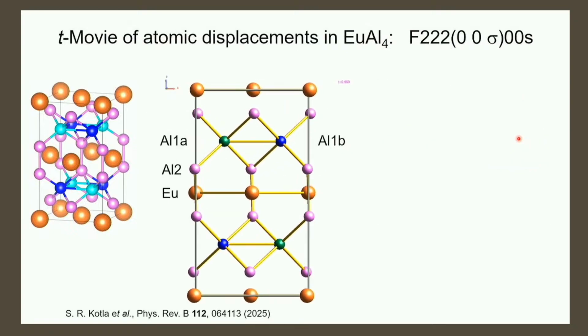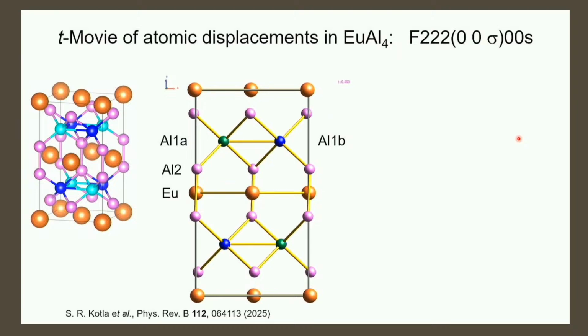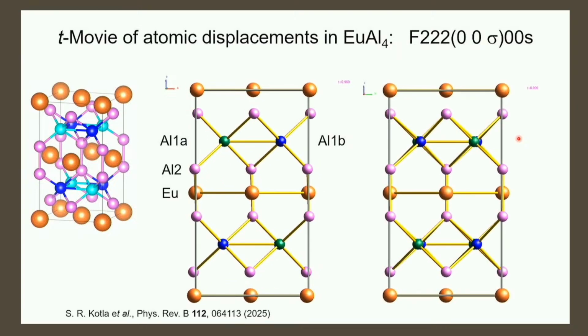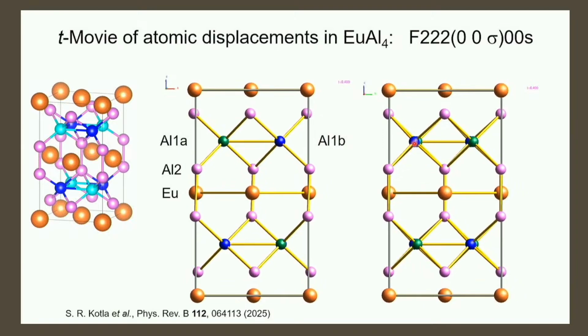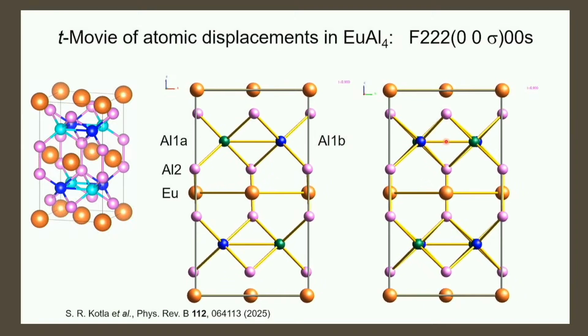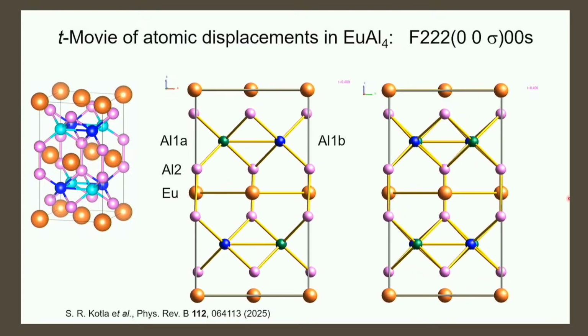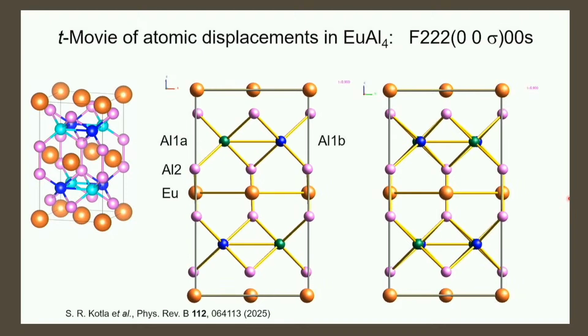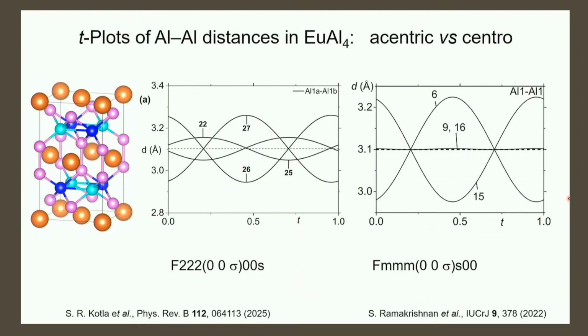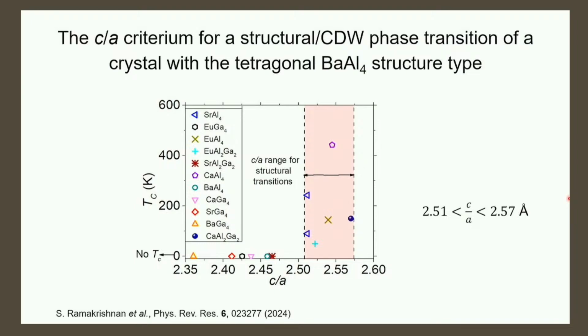You can see that here all atoms move coherently, more or less, and here the amplitude is much smaller, but you see the blue ones go left to right and make a strongly varying distance to the green ones. And that is for us then the source of the charge density wave. So I guess I will skip that, and we came up with this kind of diagram that for this particular structure type, the C over A axis needed between 2.5 and 2.58 angstrom relation, in order to find a charge density wave.